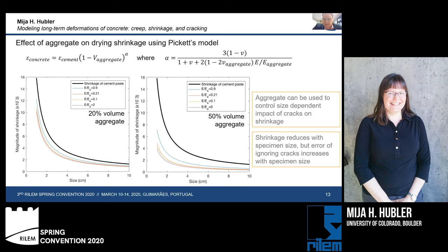So our conclusion here is that the aggregate can be used to control the size-dependent impact of cracks on shrinkage. The important point to make generally from this study is that shrinkage reduces with specimen size. However, the error of ignoring cracks increases with specimen size. As we saw earlier, the larger my sample gets, the more cracks I have. So this is something that should not be ignored.